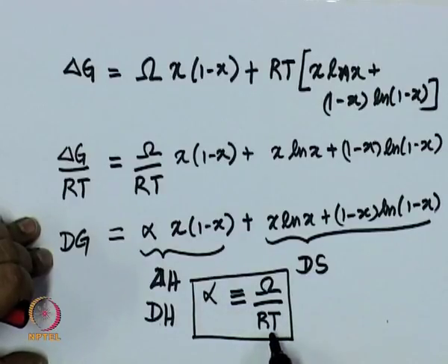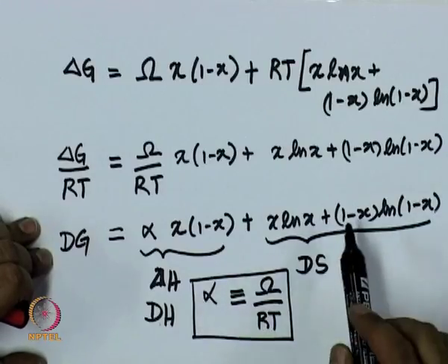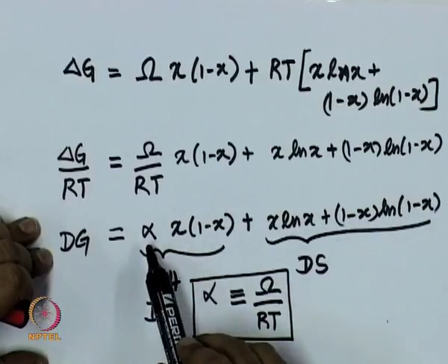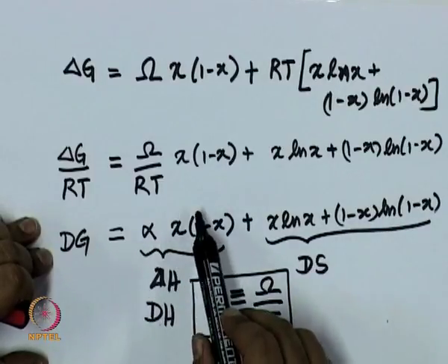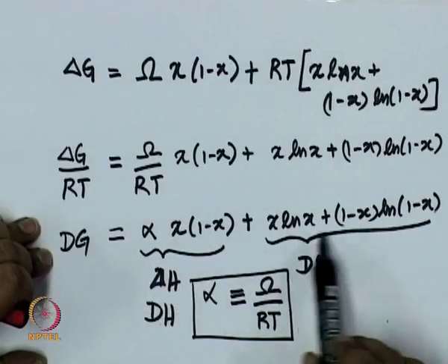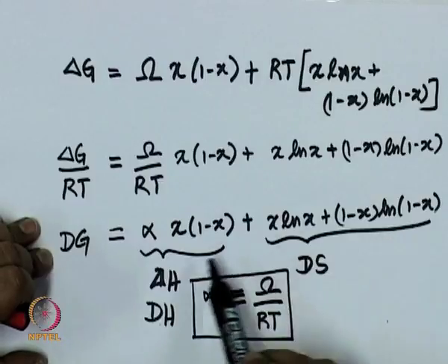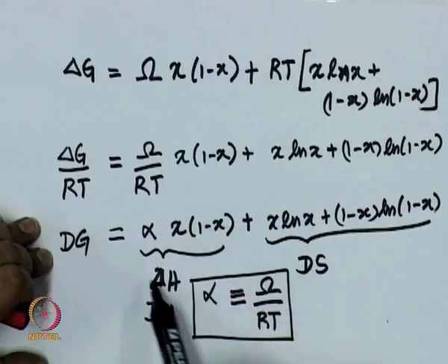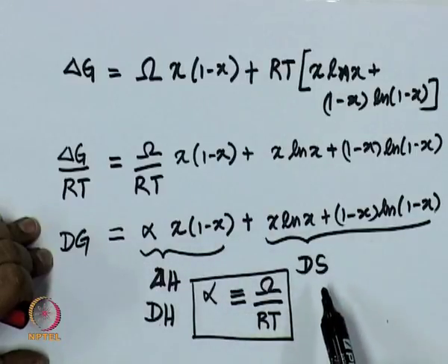This is very important, because as you remember, at higher temperatures it is always the entropy quantity which is dominant, which means alpha will become smaller and smaller. So, relatively that contribution is going to become smaller and smaller, and then the entropy term will dominate. As alpha becomes larger and larger, that means the enthalpy contribution becomes important, that means we are at lower temperatures.